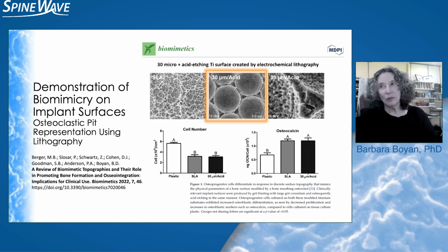So this is made exactly the same way that you would make a computer chip. It's made by photolithography. And we were looking at the crater size, which you see here. Osteoclast resorption pits are 30 to 100 micrometers in diameter. And then we acid etched it. This is what it looks like up in high mag. And you don't see those ridges, but you do see that there is a microscale and submicroscale roughness to this. And the story holds that if we now look at the cells on this surface compared to the model surface, the cell number goes down and osteocalcin goes up. So we're pretty confident that comparing cell number to osteocalcin is telling us that these cells are becoming osteoblasts.